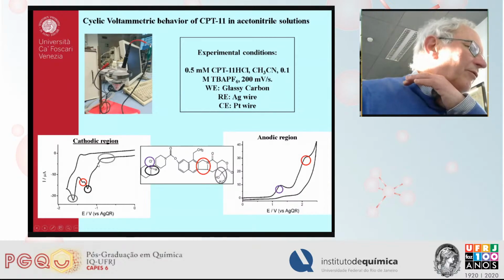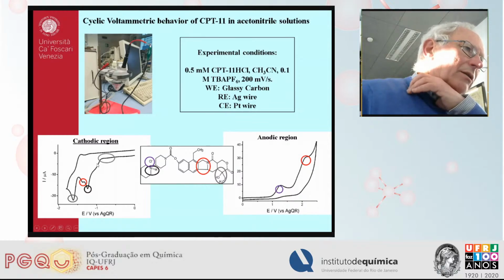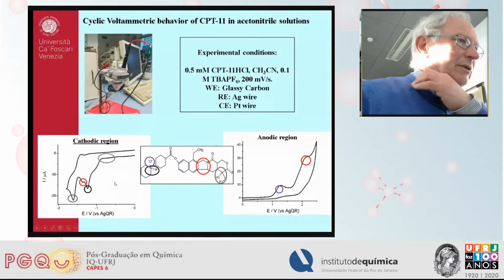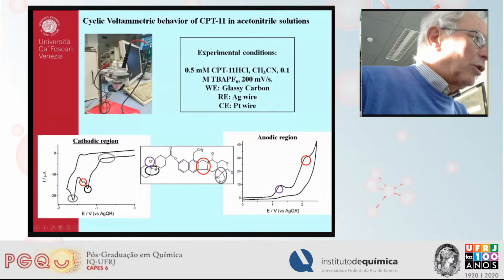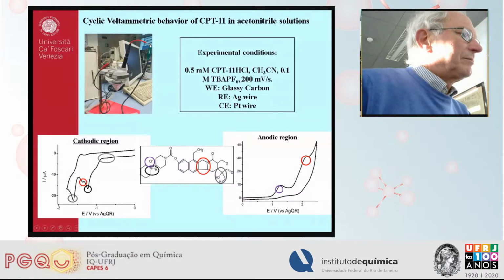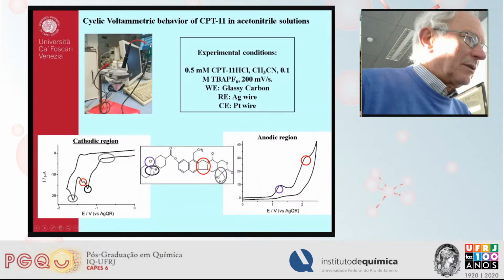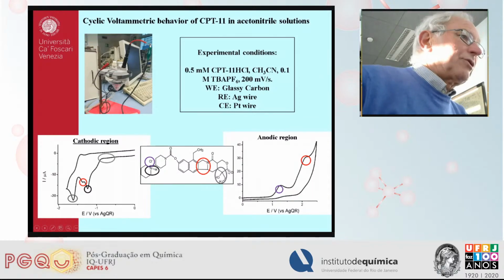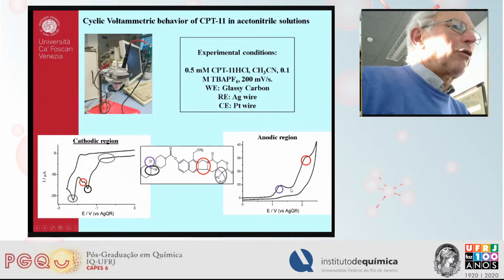So the various peaks you see here in the cathodic region and in the anodic region refer, as I told you, to different moieties of the molecule. But from our point of view, the most important part of the molecule, which provides a useful signal for the analysis of CPT11, was the tertiary amine of this part, which provides this peak here. But unfortunately, simultaneously we also get a peak due to the oxidation of chloride ions.